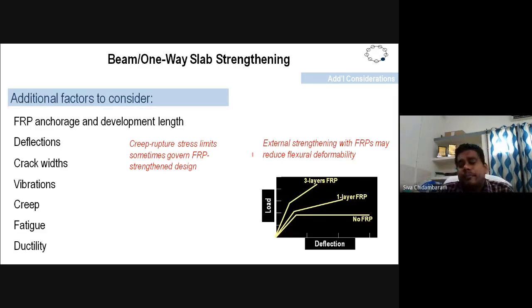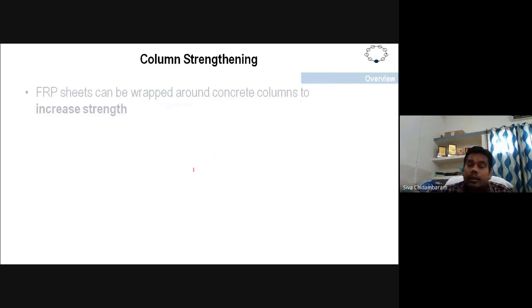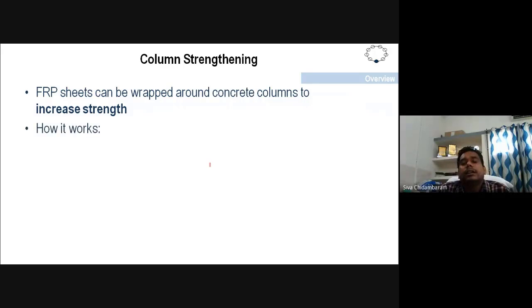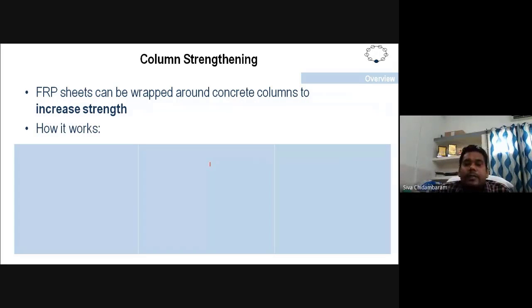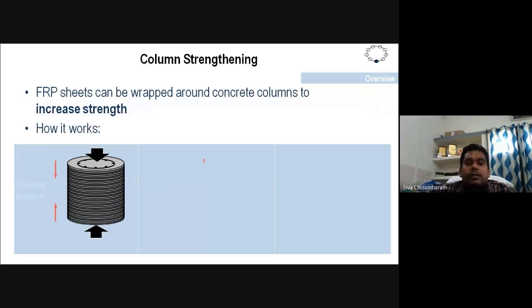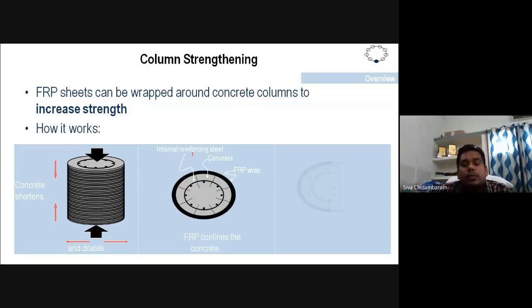When you use a number of layers, you are increasing the strength, not ductility. That's the limitation of FRP. In a column, when we apply uniaxial force, it becomes biaxial. But when you use FRP, it becomes triaxial. When you apply axial force, the concrete will try to split horizontally. That is another force, called biaxial. But when you use FRP wrapping, it gives you another force inwards, which is why it is generally termed triaxial force when you wrap FRP on columns.